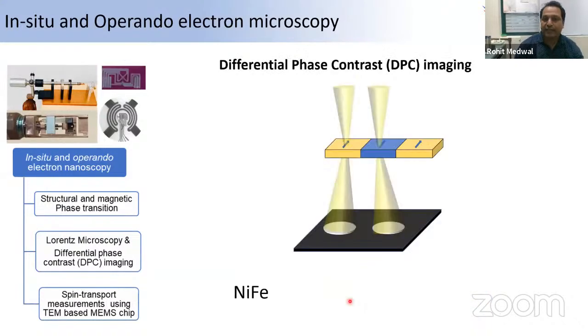We also use a second technique, which is differential phase contrast imaging. This is done in the STEM mode, where we focus the beam on the sample and do a raster scan on the sample. And the Lorentz force is very simple to understand: based on the direction of the magnetization, you can have different deflections in the system.